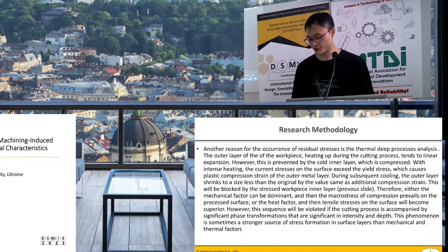Another reason for the occurrence of residual stresses is the thermal process. The outer layer of the workpiece, heating up during the cutting process, tends to linear expansion. However, this is prevented by the cold inner layer, which is compressed. With intensive heating, the current stresses on the surface exceed the yield stress, which causes plastic compression strain of the outer material layer. During subsequent cooling, the outer layer shrinks to a size less than the original by the value of the additional compression strain. This will be blocked by the stressed workpiece inner layer. Therefore, either the mechanical factor can be dominant and compressive stress prevails on the processed surface, or the thermal factor.